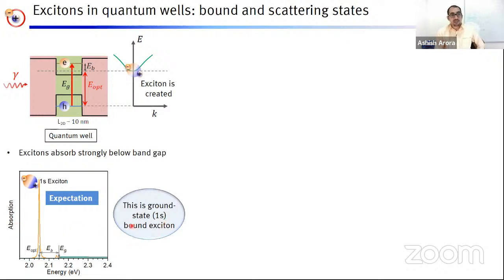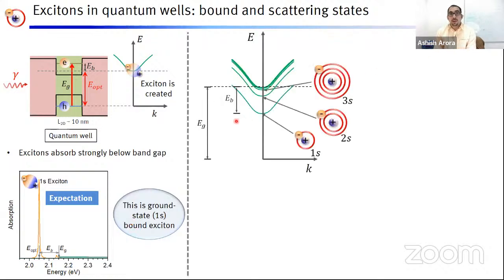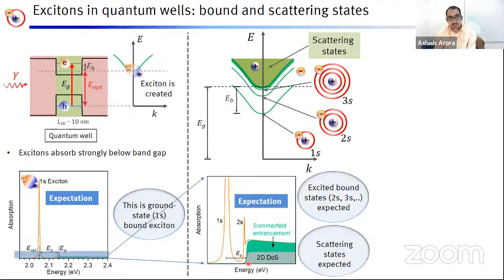Okay, but this is a ground state exciton. Now, an exciton is a hydrogen atom-like species, so it also would have some excited states: 1s, 2s, 3s, 4s, and so on. And then there is also a continuum. So a continuum is where an electron and hole can have scattering states. The electron scatters off from a hole, but still there is Coulomb interaction between them. So if we zoom into this region here, now this is the expected spectrum, this is not experiment so far. Then we find that there should be some 2s state, some 3s state, and so on, but they continuously reduce in intensity. So they are very tough to see, and also they are very close to the band edge, or the single particle band gap EB. Therefore, the line width has to be very narrow and the sample quality has to be excellent to be able to see these excited states of excitons.